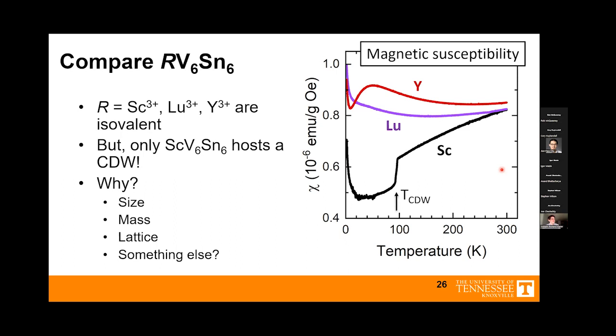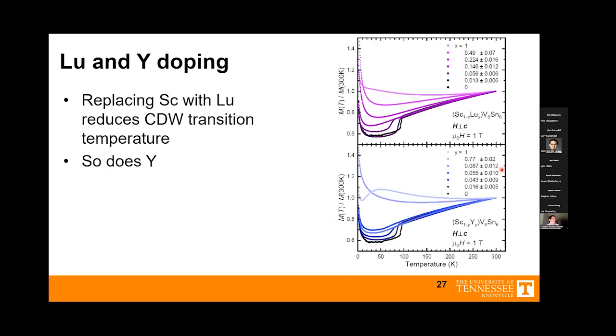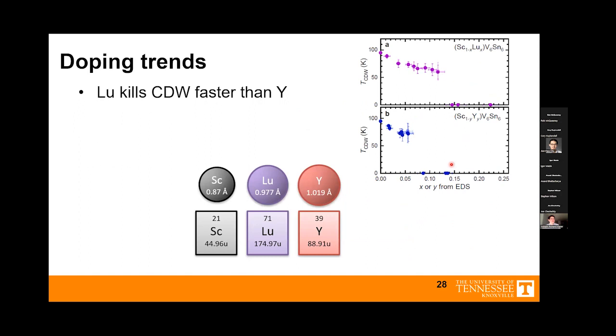So when we go between these compounds, doping with lutetium, we notice that our charge density wave, our drop in resistance here on the black curve, drops in temperature as we dope, and likewise in our magnetic susceptibility measurements. And we see the same thing as we dope with yttrium. So both of these rapidly suppress that charge density wave. In fact, by 15% doping, the charge density wave is gone.